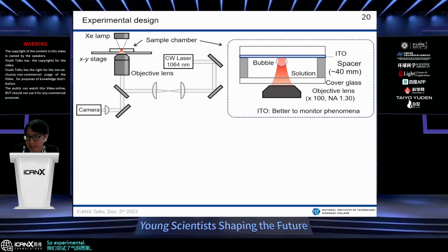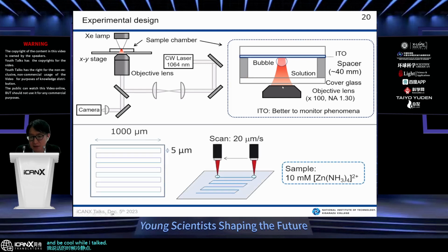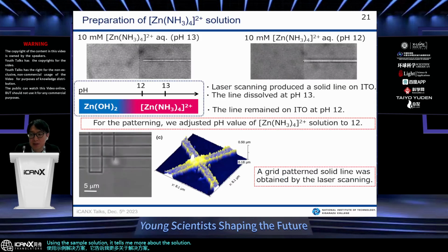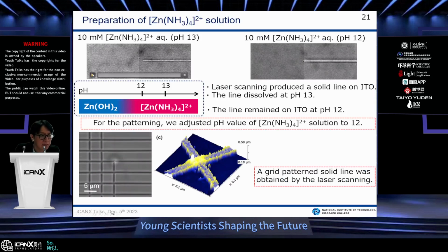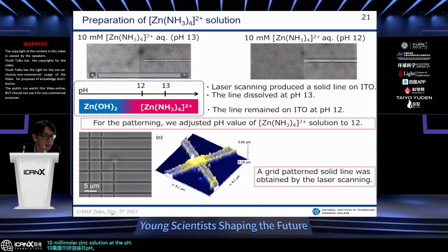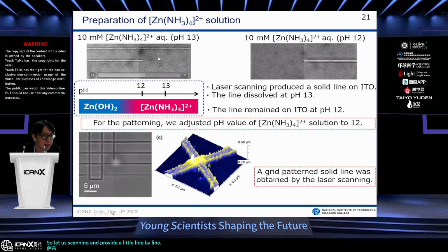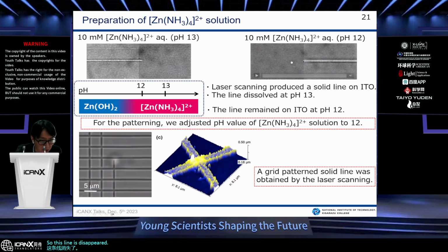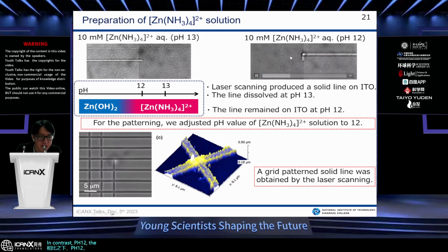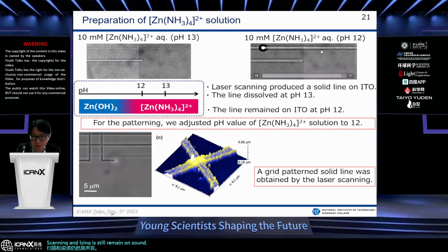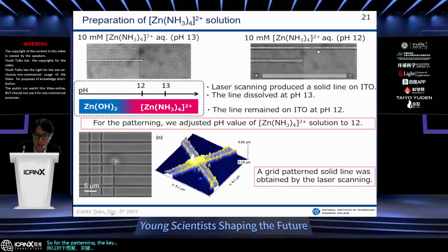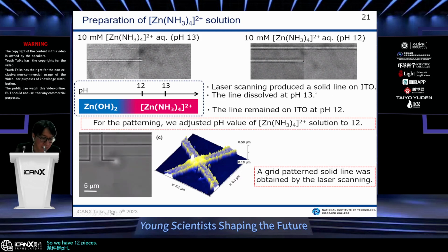The experimental design is shown here, and this system is the same as I talked about before. We scanned a laser focused beam in the solution phase, using a sample solution of 10 millimolar zinc solution. This is one of the results. With 10 millimolar zinc solution at pH 13, laser scanning provided a laser line, but this line disappeared. In contrast, at pH 12, after laser scanning the line still remained on the surface. So for the patterning, the key condition is pH. pH 12 is the best result.